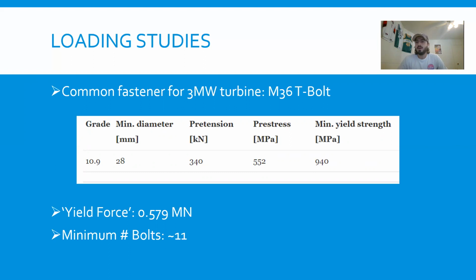Well, some common fasteners used for 3 megawatt turbines for this root joining application is M36 T-bolts. And these have a minimum diameter of 28 millimeters and a minimum yield strength of 940 megapascals. So doing a little bit of quick math, stress is equal to force over area. We can find that the yield force for these bolts would be about 0.58 meganewtons, which would mean technically with no safety factor, we could do this with around 11 bolts. I don't think 11 bolts is a good move, but technically that's what it would be.